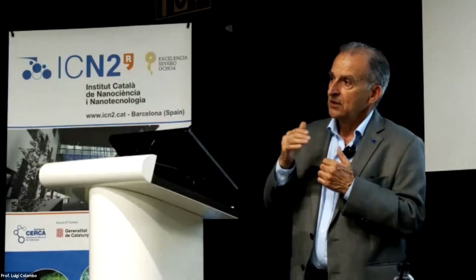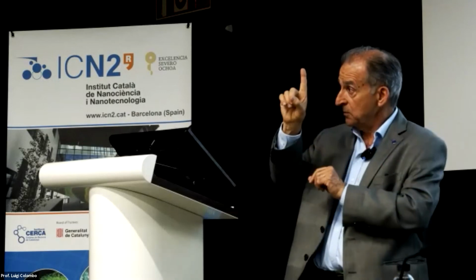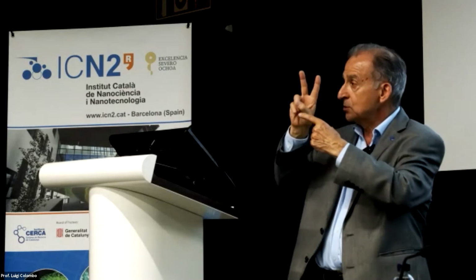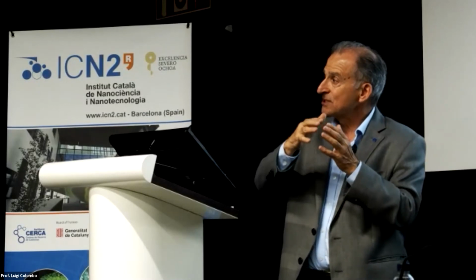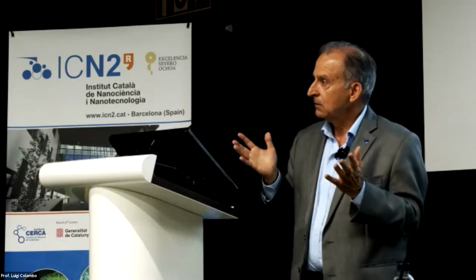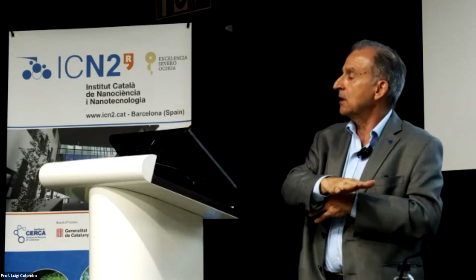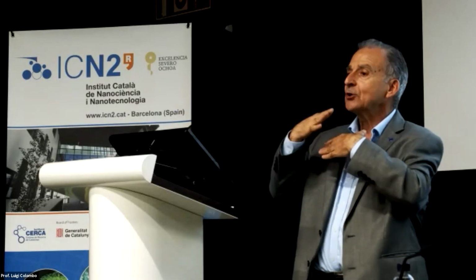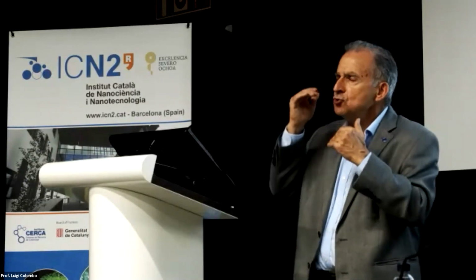Because I go back to the engineering and fundamental problems that we had with high-k metal gate, okay? The idea was to replace one material, but we replaced not only one material, we replaced two materials, and the work function. So let me go back a little bit. The company I was telling you about was trying to select a metal gate, and they used thousands of wafers to do that. It turns out that the choice of metal didn't matter. They all had different work functions, but when you process them, they all go back to the same place. What was important was actually interfaces. So they learned how to control an interface and the work function, which controls the threshold voltage of the device. And then they had to do CMP.